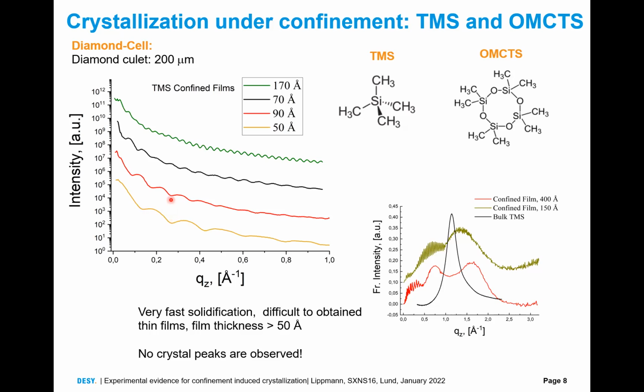To get films with different thickness, we open the gap and put new liquid inside, and so we create layer after layer and obtain thicker films. In these kinds of samples, we never observe crystal peaks, but we could observe a very nice layering even in films with a higher thickness.